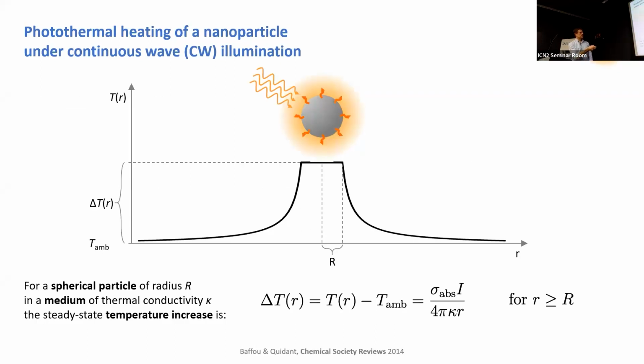It looks like this. So the nanoparticle is under CW heating, and the temperature decays as 1/r as you get out of the particle. And in fact, the temperature inside the particle is rather constant. The reason for it is because the thermal conductivity of metals is typically orders of magnitude higher than the thermal conductivity of anything outside of a metal, and so the temperature equilibrates quickly inside. And this is interesting for us because this means that at the surface of the nanoparticle, the temperature is going to be high, chemical reactions are going to be very fast, and as soon as you're a few nanometers away, the chemistry will stop.